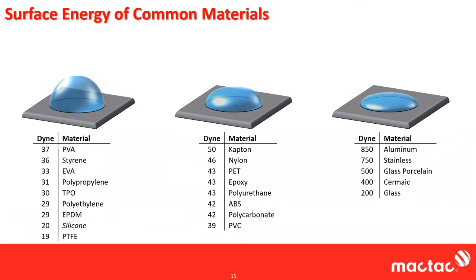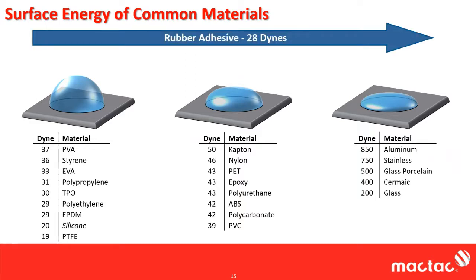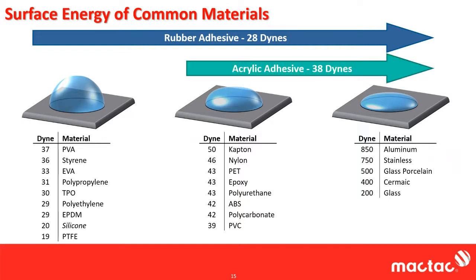So going back to the original statement I proposed, that MacTac usually starts with rubber-based adhesives. The reason is that rubber-based adhesives typically all fall around 28 dynes. So rubber-based adhesives cover the largest range of materials to which they'll adhere and really wet out. They're about 28 dynes. There's not a lot of fluctuation there. An acrylic example, though, the low end of an acrylic adhesive is about 38 dynes.